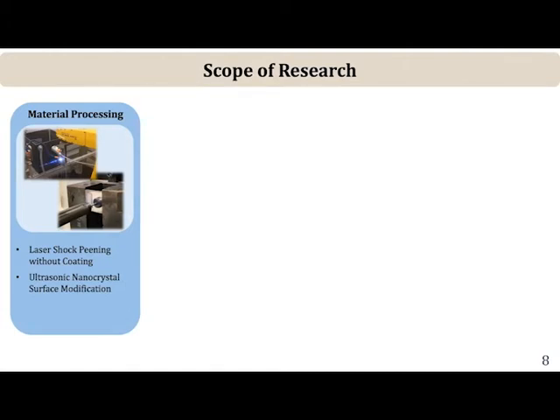These were thick plates. And as you know, the properties of these plates can be quite anisotropic. You have an elongated or partially recrystallized kind of grain structure. So it depends very much on direction; the short transverse direction typically is the weakest and most prone to fatigue cracking. So we have to take care when you do these treatments and the testing, that you test the material under conditions which are going to be the worst in terms of loading relative to the microstructural features. So 2 techniques.